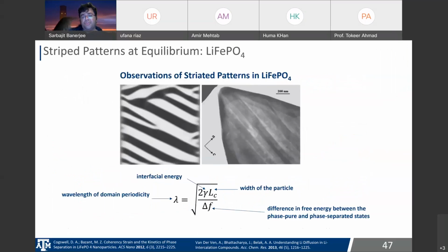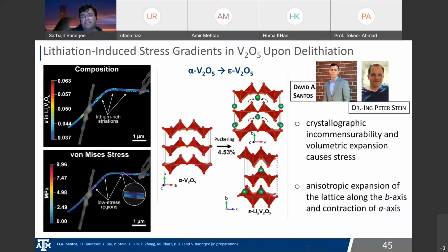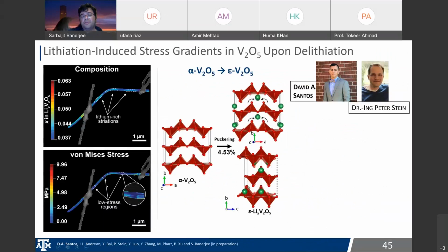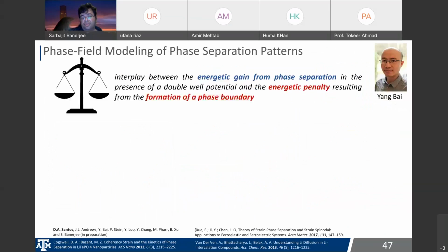This is not just restricted to V2O5, which is our work that I showed you here, but this is work that has been done on lithium iron phosphate, for instance, where you also see these striations, with very periodic conditions, depending on the free energy separation between phase-pure and phase-separated states. So the point of this is to say, look, we've got these large stresses, von Mises stresses, for instance, plotted here, even within one particle, because of the complexity of the intercalation reaction and the phase transformations that are accessible. The interplay of geometry, the separation energy between phase-pure and phase-separated states, and the elastic misfit at phase boundaries gives rise to some very sharp or substantial stress gradients.